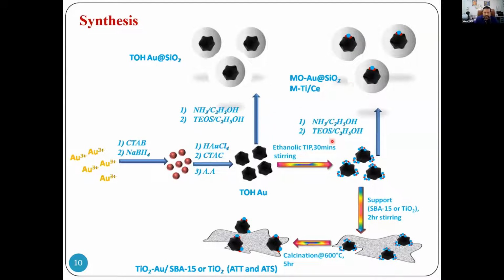This is a synthesis methodology that we have formulated. Again, I'm not going to go into the details because of the want of time. You can make this gold nanoparticle and put it on a high surface area support like TiO2 or an inactive support like silica. You can also do an encapsulation where this gold trisoctahedral nanoparticle can be encapsulated in porous silica.